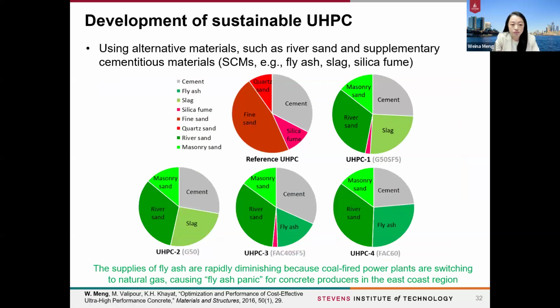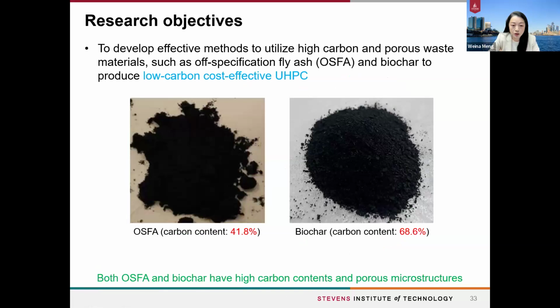So for now, the major work on developing sustainable UHPC materials is to replace the cement with a high volume of supplementary cementitious materials such as slag and fly ash. However, those typical supplementary cementitious materials are really in high demand. And also it's reported that the supplies of some SCMs are diminishing. And there's really a need to find some alternatives. So in our work, we try to find the alternatives, specifically the high carbon and porous types of wastes to replace cement to develop low carbon and cost-effective UHPC. The high carbon waste materials I will introduce here today are the off-specification fly ash, OSFA, and the biochar.